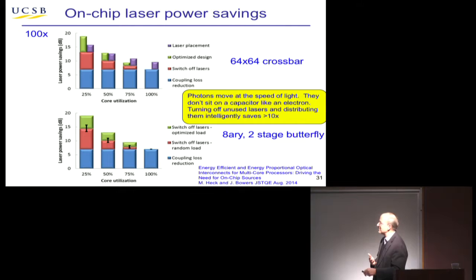And so some of it's the coupling from the laser onto the silicon chip. Some of it's from the fact that you can turn off 3/4 of the lasers and not use them. Some of it's because you can intelligently place the lasers where you'd like to. So rather than have some tree architecture from an off-chip fiber, you put the lasers where you'd like to have them and don't have all the distribution losses. So you gain a lot. Power is a big issue in all of these structures.